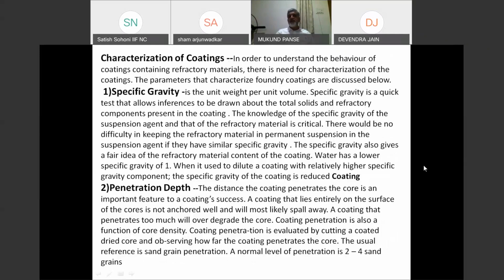is the refractory content. Basically, it is refractory content in the paint. The higher the refractory content, the specific gravity will be more. It can be measured, but not very easy to be measured. Penetration depth. When you are applying a paint, to what depth it has penetrated in the core or mold surface. You cannot say it is more or less, it is the required depth to give you a better surface finish. For a higher thickness of metal, you should have better penetration. For a smaller mold, you can have a smaller metal thickness.